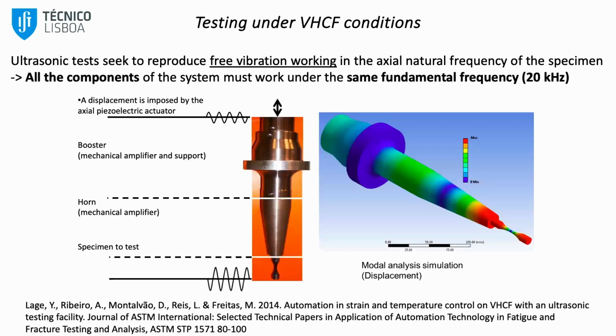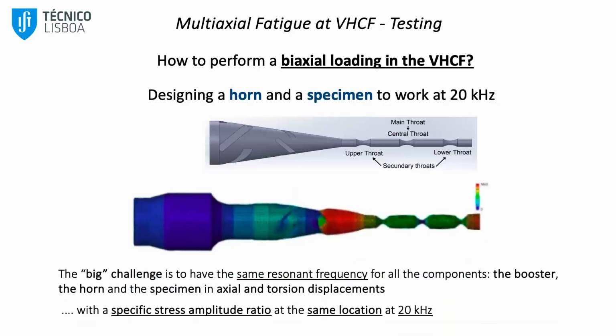Okay, so the question now is how to produce a biaxial loading in very high cycle fatigue conditions. Regarding the uniaxial test, this is well defined and we have an analytical solution for this and also FEM. But for a biaxial loading case, it's not so easy. So we need to design a horn and a specimen so that all the components are working at 20 kilohertz. So this is our proposal.